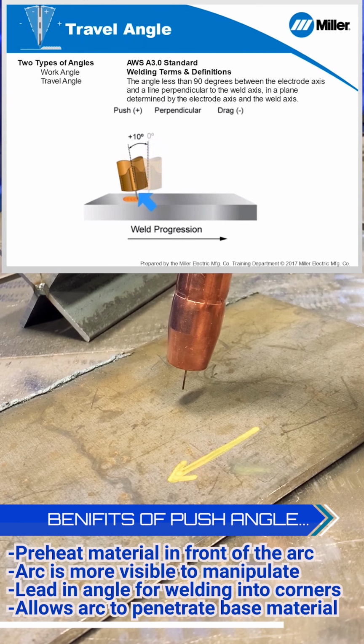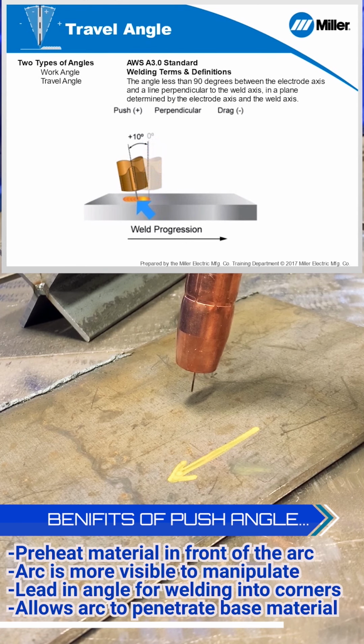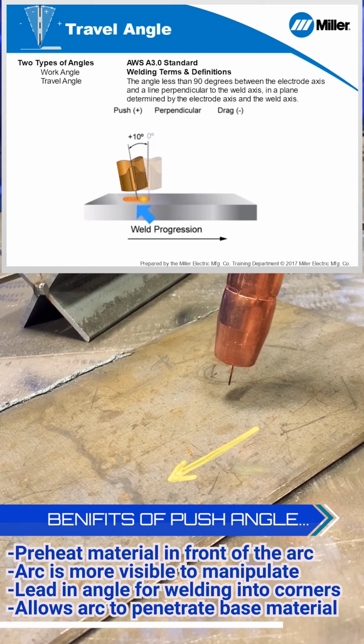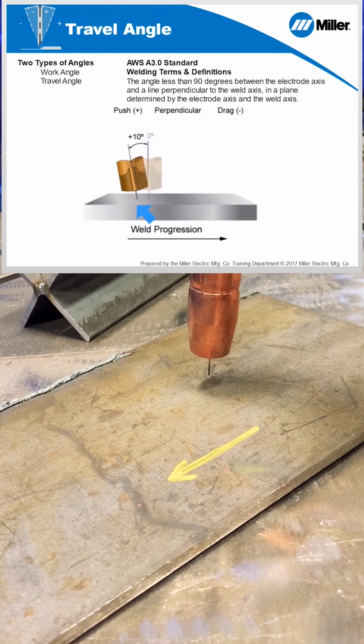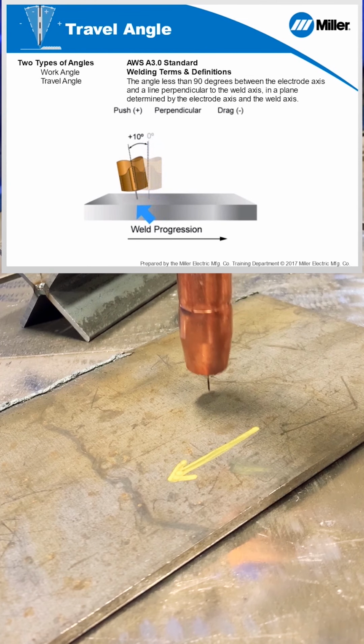That combined with my contact tip to work distance being favorable, I'm going to be able to see the molten puddle. So this is a really critical feature when you tie everything together between my work angle being 90 degrees, and then I've got about a 10 to 12 degree travel angle here. And then I've got my contact tip to work distance set. So now by tying all 3 of these parameters together, we're able to produce a weld that is acceptable for our quality standards. Number 6 on the list of essential 7 variables is travel speed.